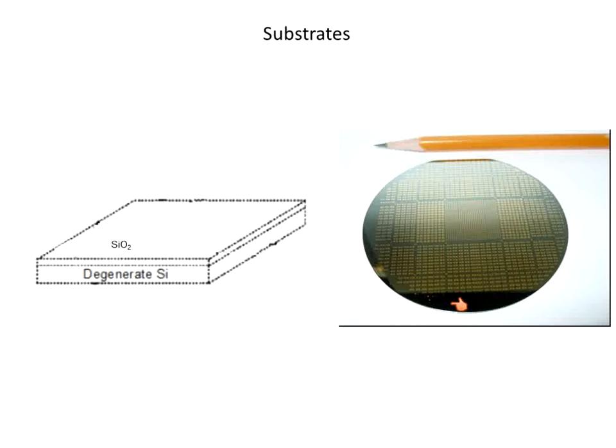And on the silicon wafer, which is about 3 inches, we can pre-pattern gold electrodes. All of these squares that you see over here are gold electrodes that can be pre-patterned using lithography. And this is the substrate on which I capture my fibers. Remember, to get a single fiber, I would take this substrate and pass it very quickly in the space between the tip of the needle and the aluminum foil. That's how I get single fibers that cross this substrate. As they fall on the substrate, they are flexible and they are charged, so when they impinge on the substrate, they stick.